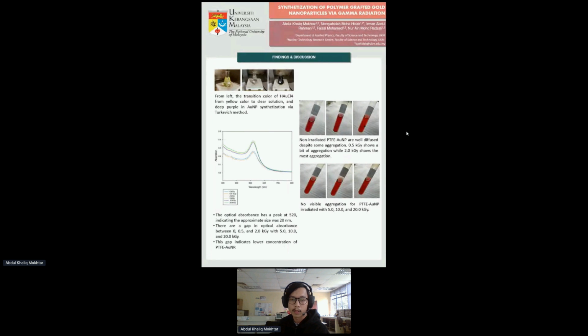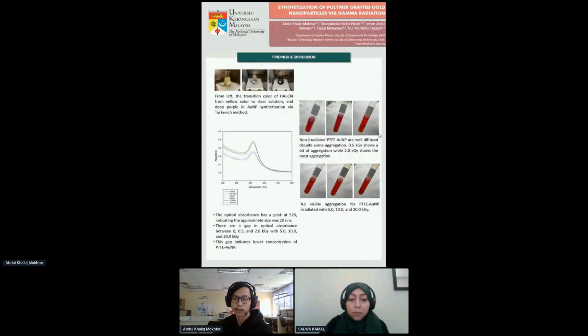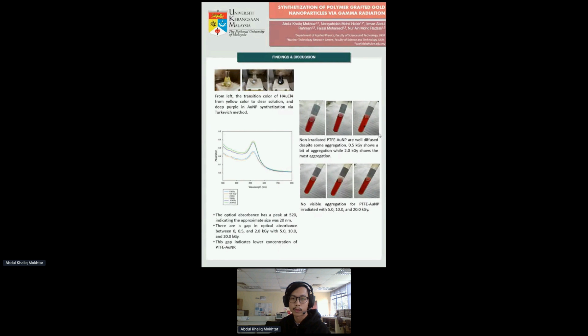There's a gap in optical absorbance between 0, 0.5, and 2 kilogray, and 5, 10, and 20 kilogray. As we can see, there's a gap. This gap indicates a lower concentration of PTFE gold nanoparticles. The non-irradiated PTFE gold nanoparticles are well diffused despite some aggregation. 0.5 kilogray shows a bit of aggregation, while 2 kilogray shows the most aggregation. And there is no visible aggregation for PTFE gold nanoparticles irradiated with 5, 10, and 20 kilogray.